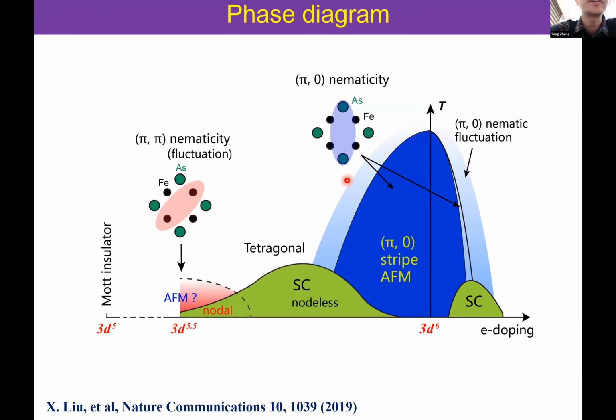So we can plot this phase diagram. Close to this 3d5.5 configuration, which is the potassium 122 system, there's a pi pi nematicity or fluctuation. Such C2 symmetry breaking is also observed above the Tc, so there could be a fluctuation. But at the optimal doping, the nematicity would disappear, and the electronic state recovers to the tetragonal.